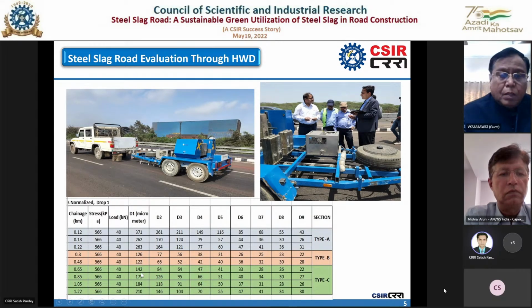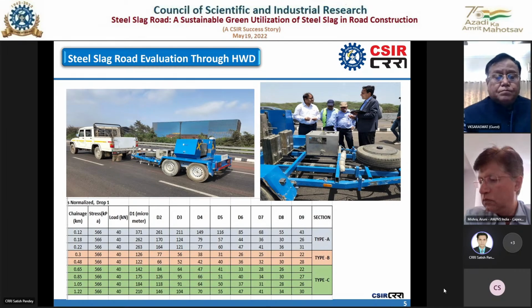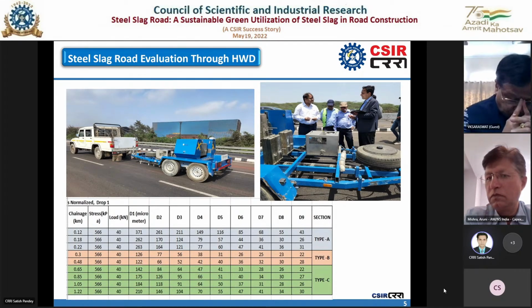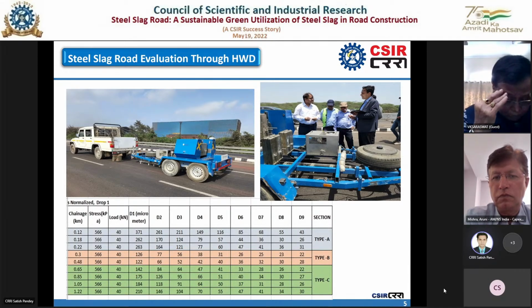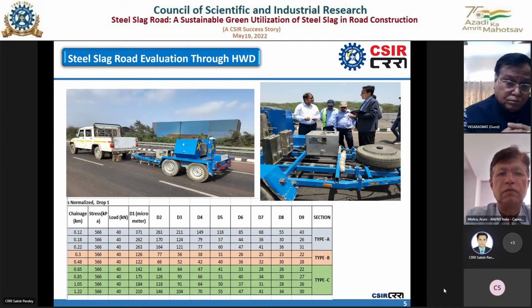By virtue of that, this particular road is considered stronger than the road built through natural aggregate, and we can effectively reduce the overall thickness of the road by 30 to 40%. So this is one of the major benefits of constructing a road using 100% processed steel slag aggregate. We can not only prolong the service life of the pavement, but also conserve the natural aggregate and natural resources for the construction of roads in the country.